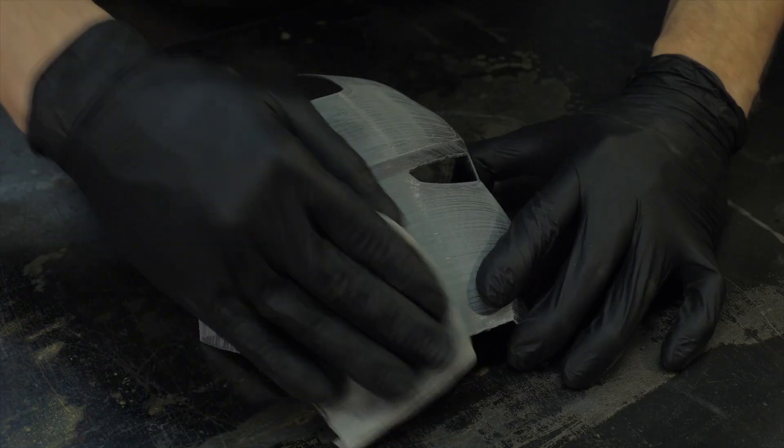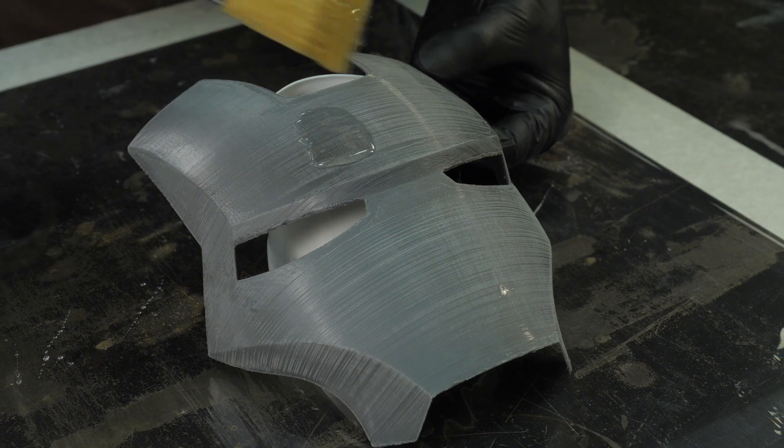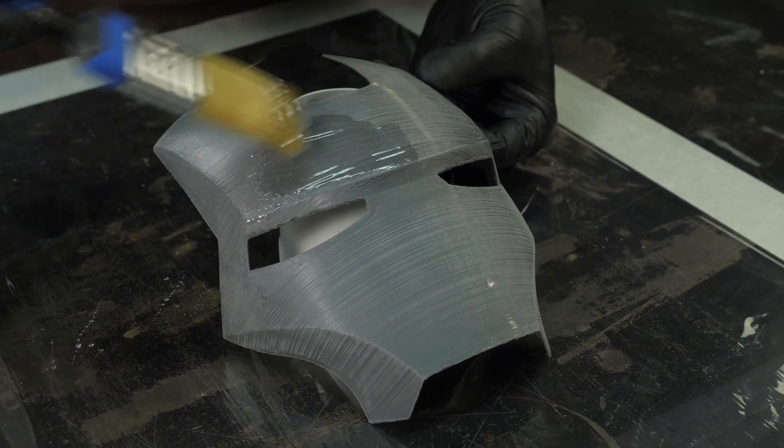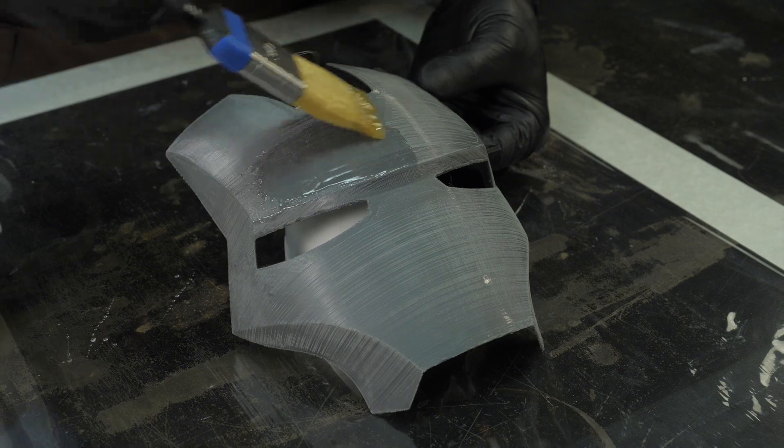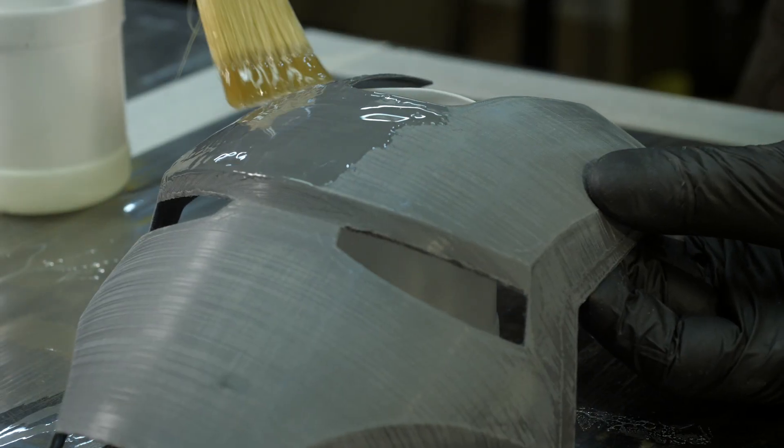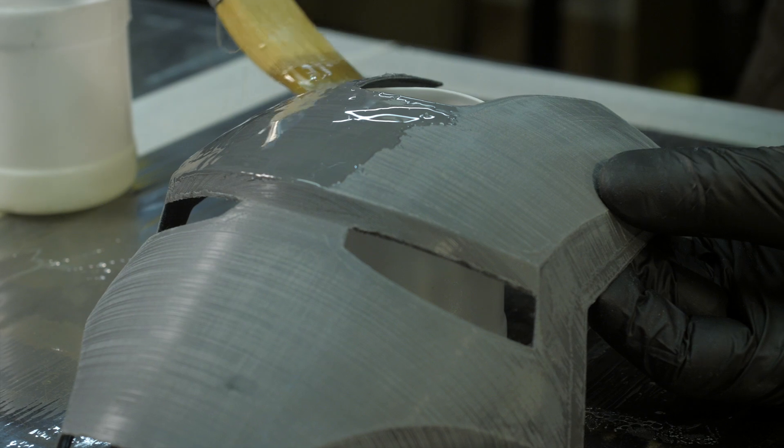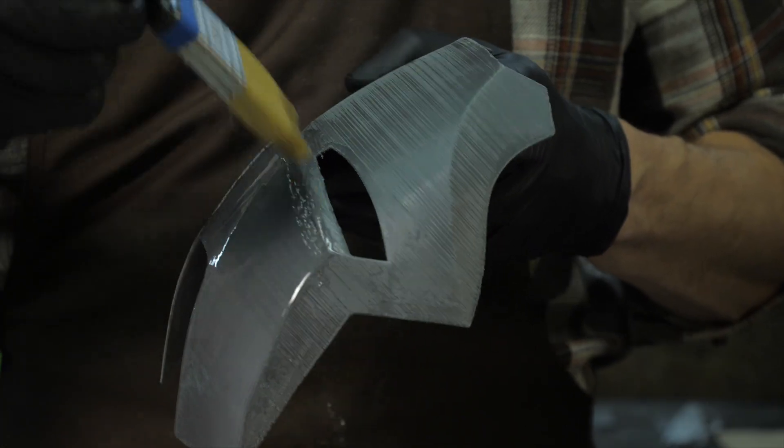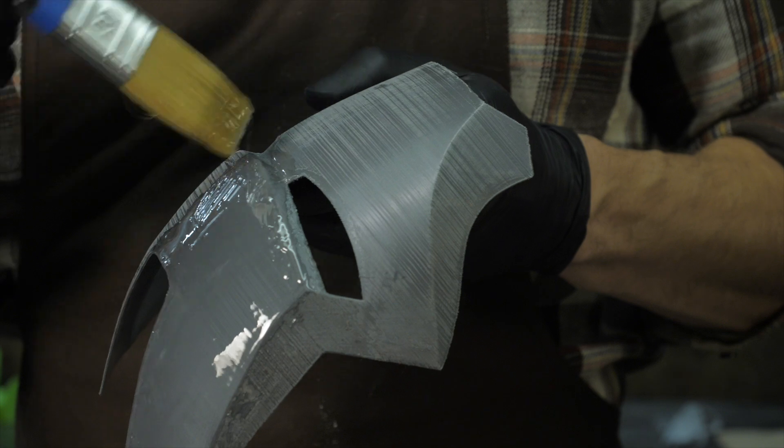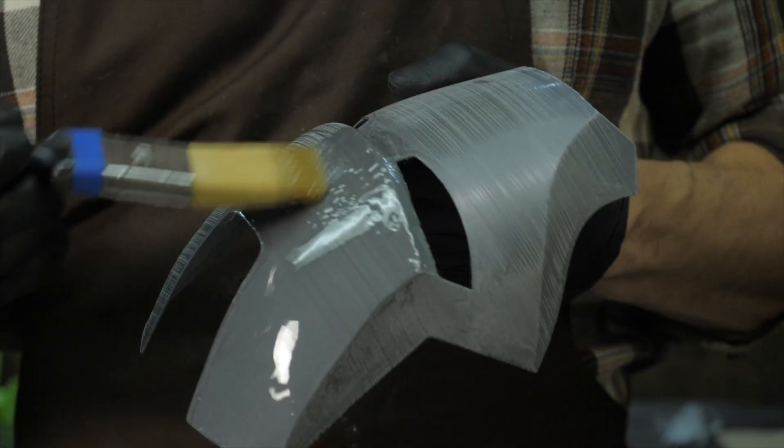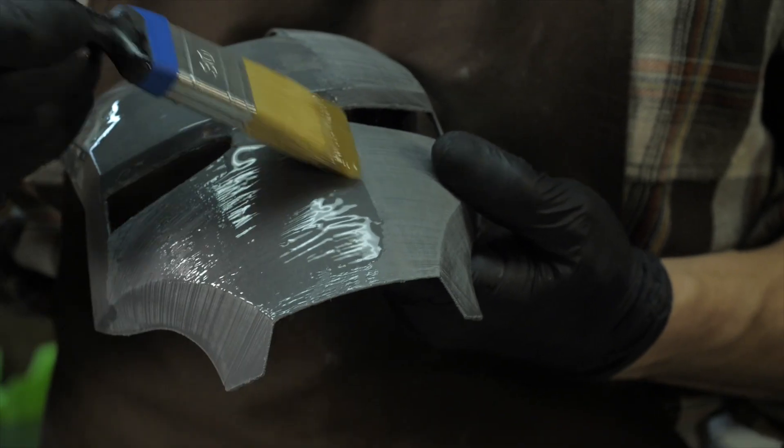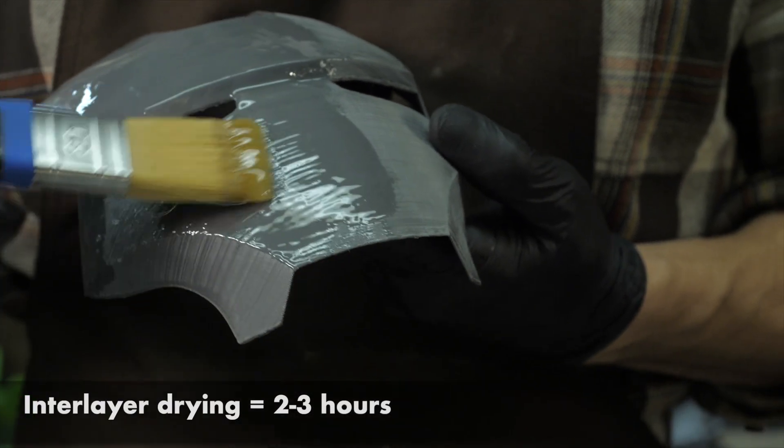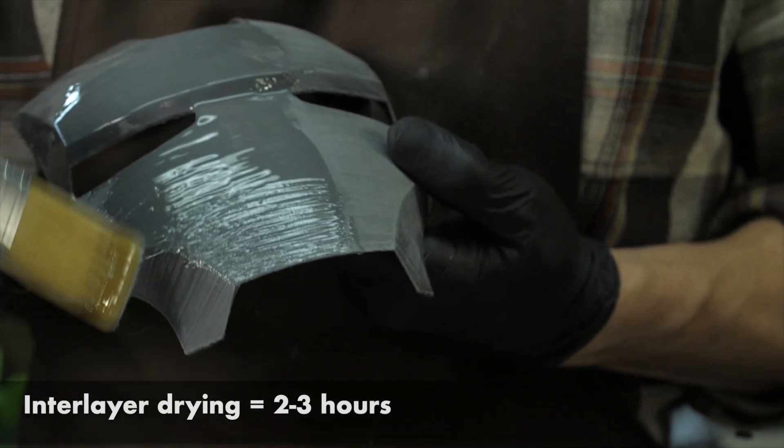Degrease the part with a solvent and cover the front side with a thin layer of structural epoxy resin. This layer is needed in order to provide parts with sufficient rigidity for further processing. And if there is a task to minimize the weight, then this layer will be the outer finish coat. If there is a need to apply another layer to provide a greater margin of thickness for subsequent grinding, then the ideal moment for this is after 2 to 3 hours, when the first layer has already set, but is still sticky.